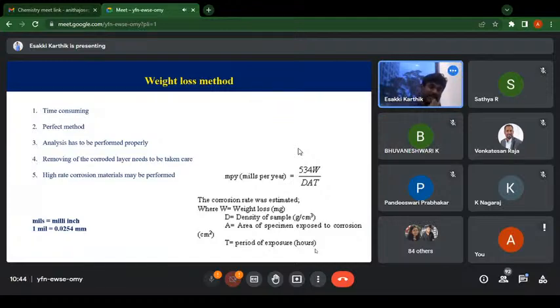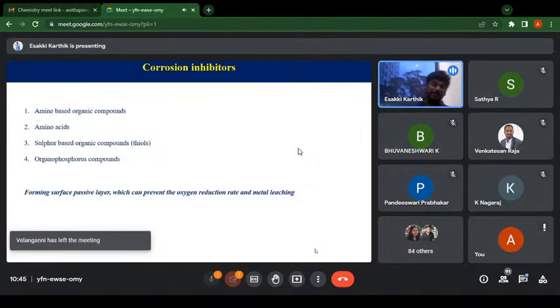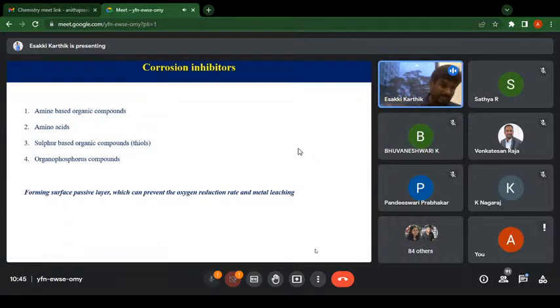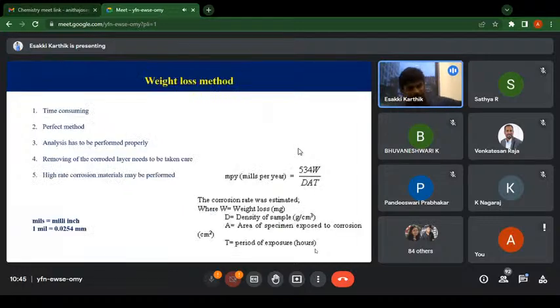The only problem is where you are using a corrosion inhibitor. Let us say that normally the corrosion rate is very high. When you add some inhibitor like amine-based organic compounds, amino acids or sulfur-based compounds, these compounds will form a protective layer on the metal surface. This protective layer won't allow the corrosion process, and slowly it will slow down the corrosion rate. When it slows down the corrosion rate, you have to wait for at least some small layer to form. It will form after 2 months, after 3 months, even sometimes 6 months. When your inhibitor is working very well to prevent the corrosion, you need to wait a very long time.